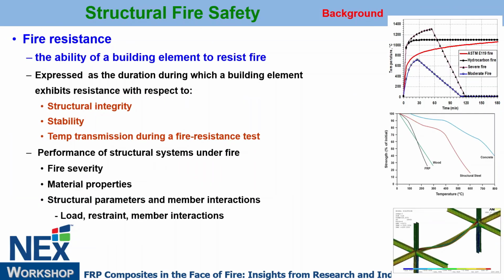And this fire resistance depends on a number of things, including how severe your fire is. Right? So for a bridge, fire is much different than a building fire. And when you have FRP, your fire scenario changes. In fact, as Steve was pointing out, we have done a lot of tests over my career. Doing FRP tests, I'm always nervous and I don't want to do the test because it's hard to maintain in the furnace a certain temperature. Just like wood, it starts to burn. To control my burners, to put less fuel, it's a big challenge, right? So that's a problem.